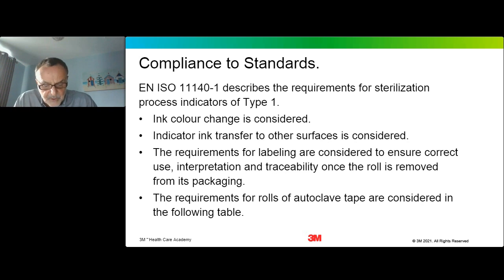including the instructions for use, which must contain, and most importantly contain, the actual information about the colour change that the tape undergoes. And this is something which is often not adequately communicated to the OR teams, particularly if a new tape is introduced with a different colour change. Most autoclave tapes might go from cream to black, but there are some which go from a red colour or a green colour to a darker green or a black colour. And of course, this can be confusing to end users if they haven't been told that the new tape you're going to use has a different colour change.